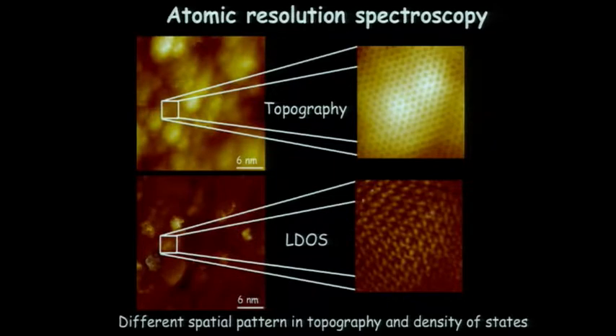If you were to look at these two closely, or take a Fourier transform of them, you would find that the periodicity in the density of states does not actually match the topography. So there are some other periodicities going on in the sample. In this case, it's from some kind of scattering in the sample. We can learn something about the band structure of the sample by taking these images where we do spatially resolved density of states measurements and looking at how the wave vectors differ from just the atomic lattice. Those are the three types of measurements I'm going to show you today: topography measurements, spectroscopy, and also a little bit of these density of states measurements.